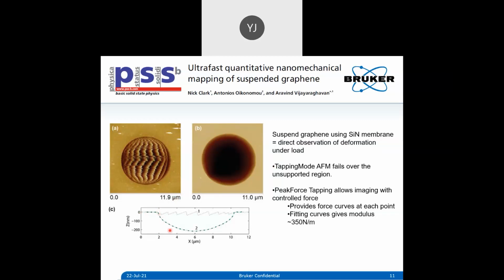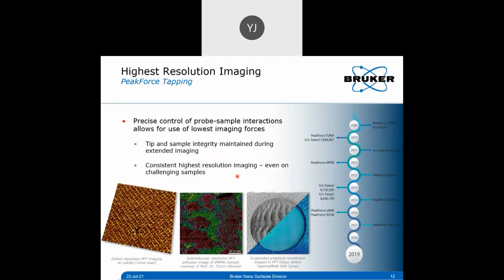You can see this is the substrate, and there is the bowing of the graphene film, and then you have the substrate again. So very nice image you can get. And this allowed the user in this case to study the mechanical properties of the graphene without being affected by the substrate, right? So they can do the modulus fitting, and they found the modulus is about 350 Newton per meter experimentally, right? So this is one of the interesting data.